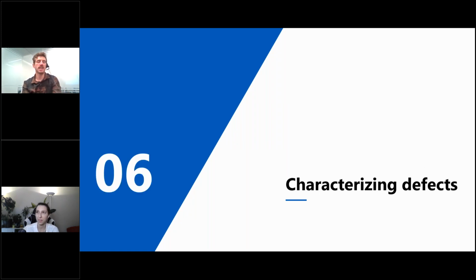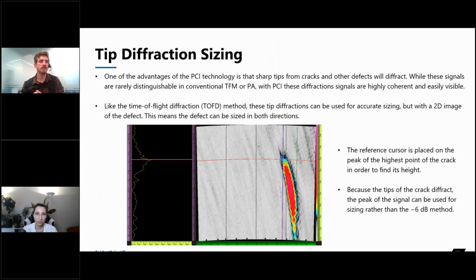So moving forward into how we can actually use PCI to have a better characterization of defects, because that's going to be one of its main advantages that we've been mentioning since the beginning, that it's easier and better to do sizing and characterization than with amplitude-based techniques. So the first bit is actually using the tip diffractions to do sizing. One comparison we like to make is that time of flight diffraction, TOFD, is often used for some of the same kinds of defects in order to size them. And it's the same idea: we're looking for the change in phase in our A-scan in the TOFD, and that's how we're going to size the defect rather than using the amplitude of the signal.